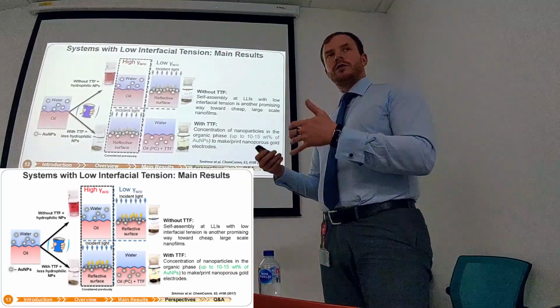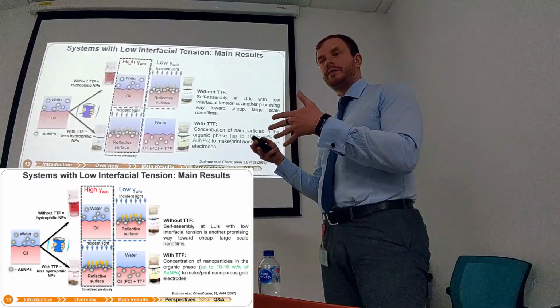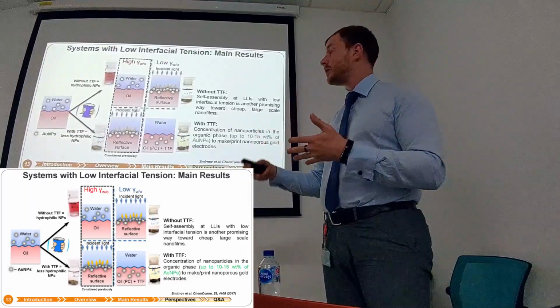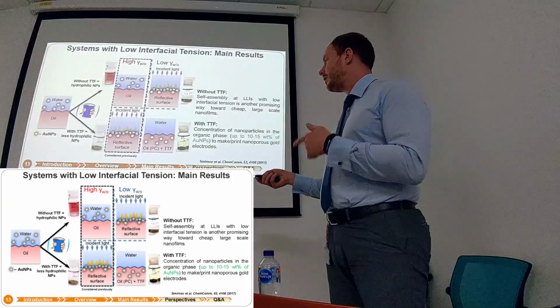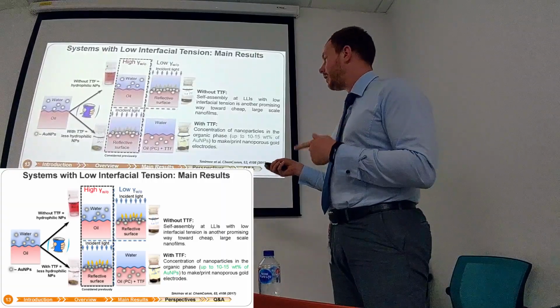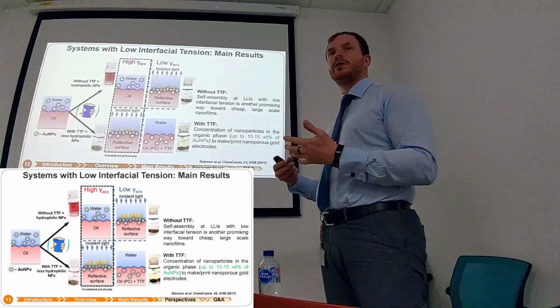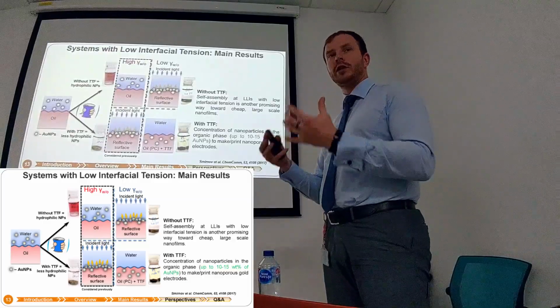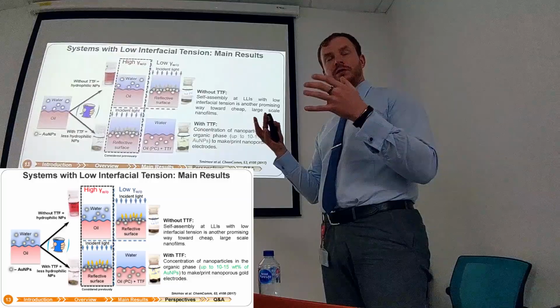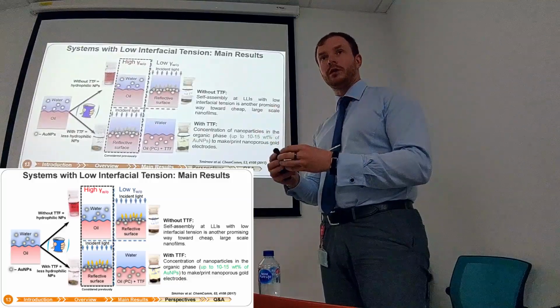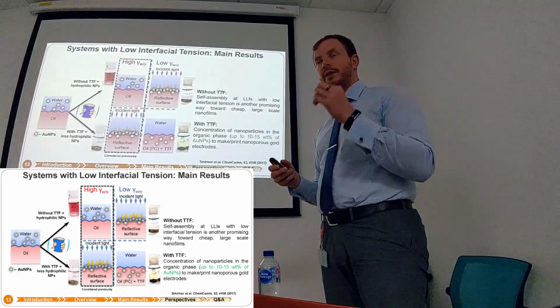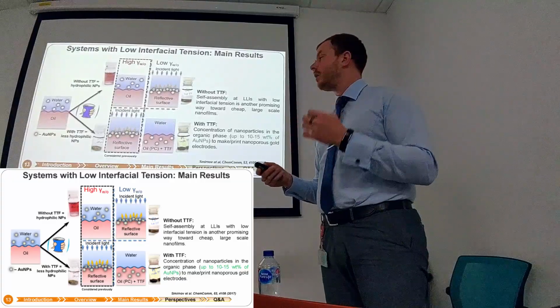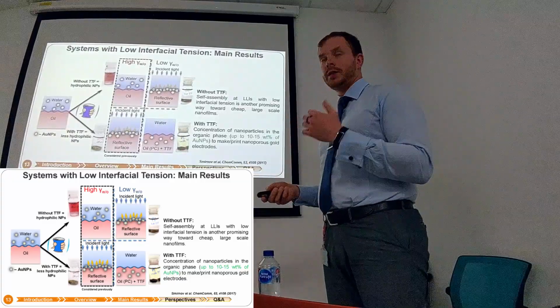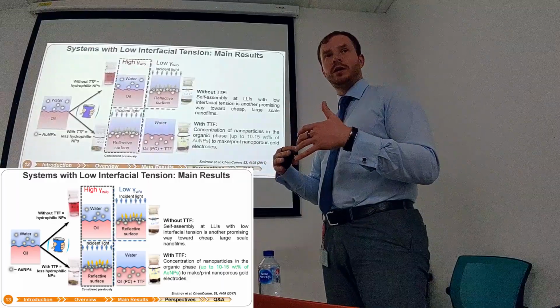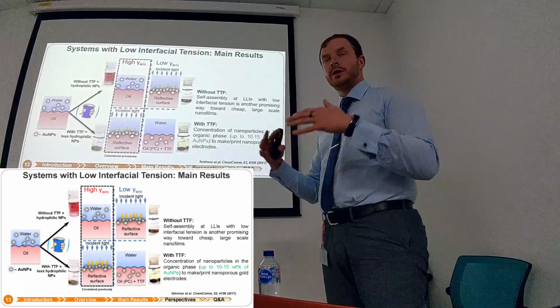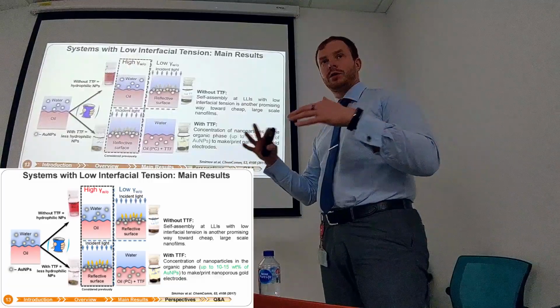And again, this is because of the very unique nature of TTF. The most important point here is that in principle we can concentrate these nanoparticles. We start with a reddish solution, we transfer those nanoparticles to propylene carbonate, and then we finish with an intense dark color of the droplet here. It's simply because the absorbance is so high, and the peak is so broad, that it absorbs all the light.